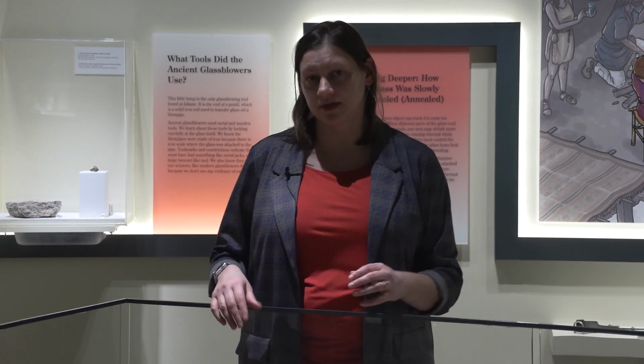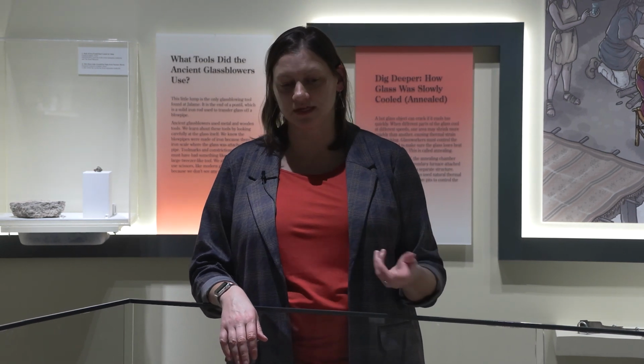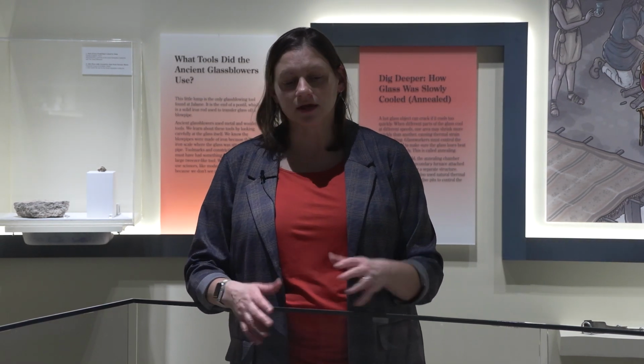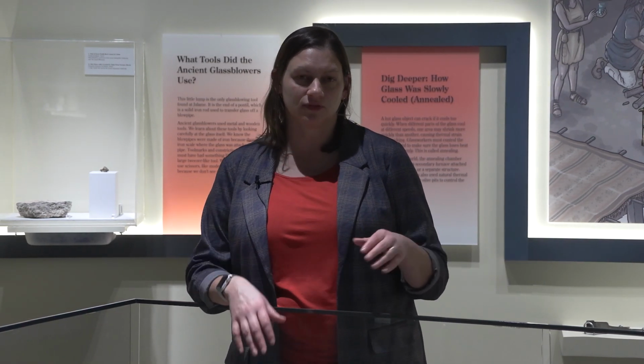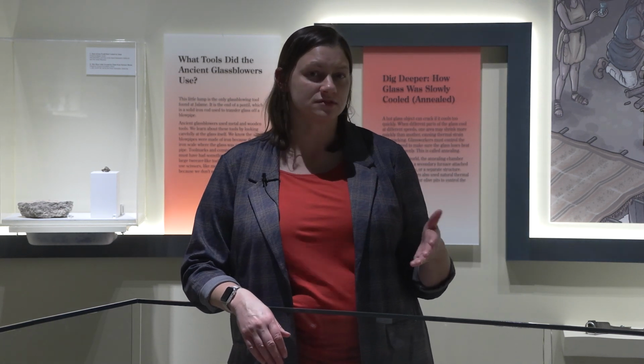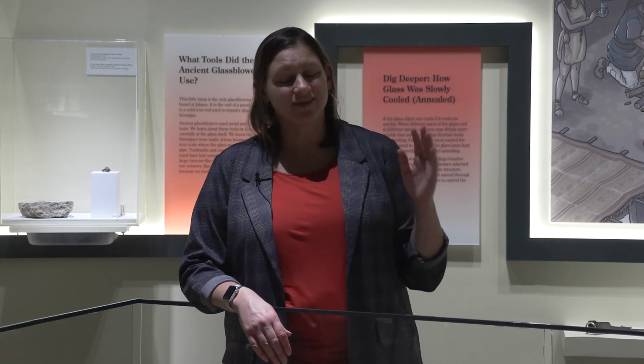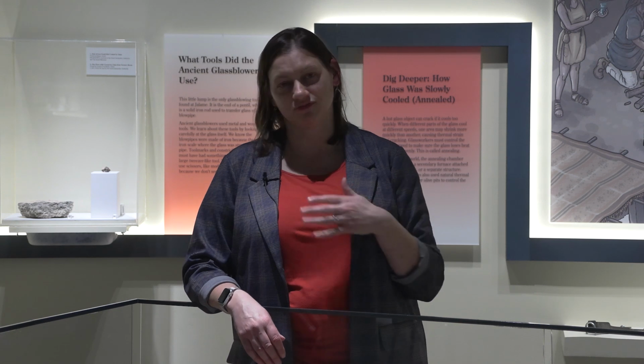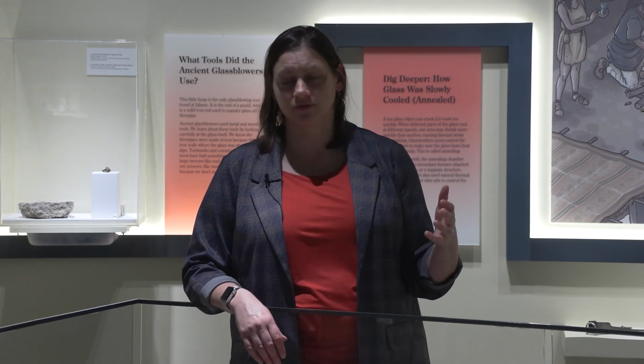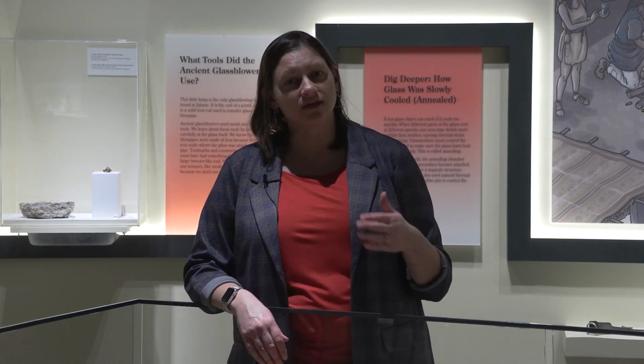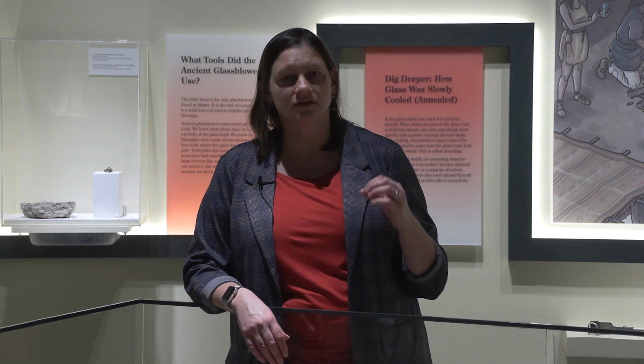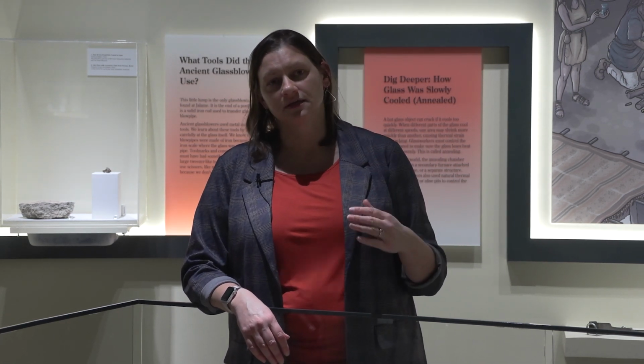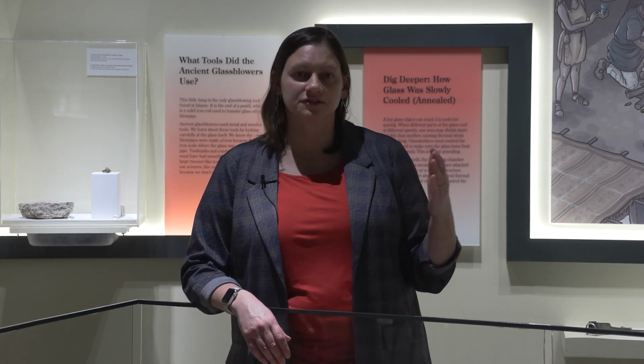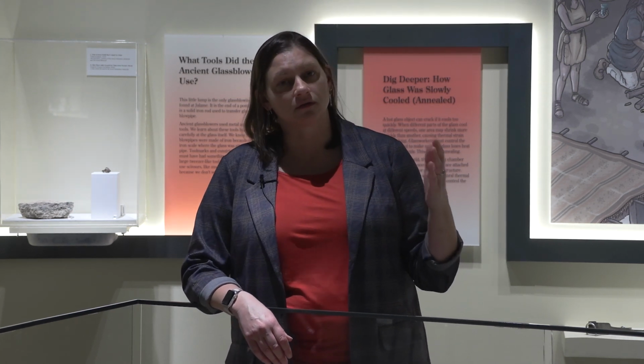had the same problems that we have with modern furnaces, and it would have needed to be replaced. And all kinds of other evidence points to the fact that this workshop was only active for a relatively short period of time, and that pattern is consistent with glass workshops that we find throughout the rest of the region as well. And what we think is happening is that we have semi-itinerant glassworkers who are moving essentially from site to site, building new furnaces, probably locating different fuel sources.